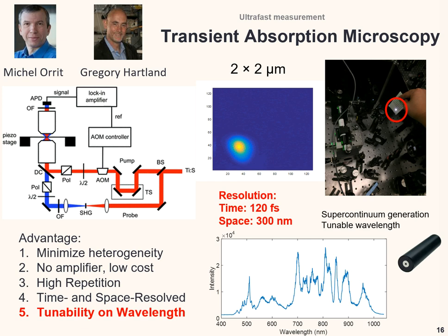It is not a very easy job, because to generate a supercontinuum, your laser pulse energy should be high enough. But in a single particle measurement there is a trade-off: if you have very high laser energy, you will destroy the sample very easily. So I developed this system, and we optimized the whole system, which helped us to realize this single particle wavelength tunable transient microscope.